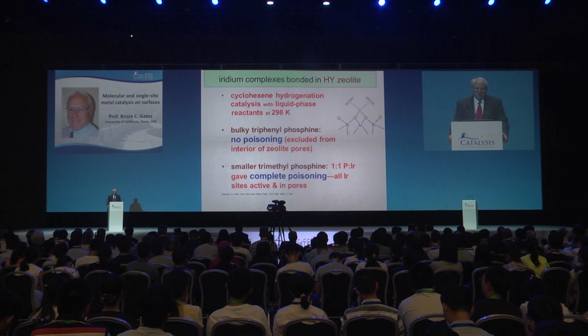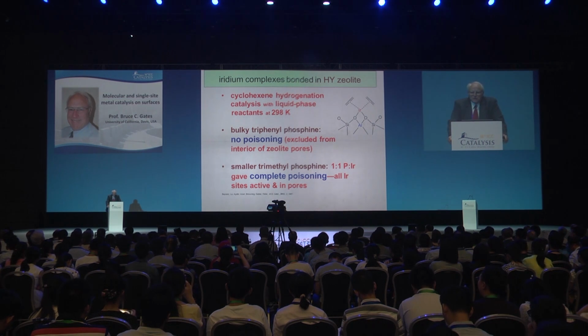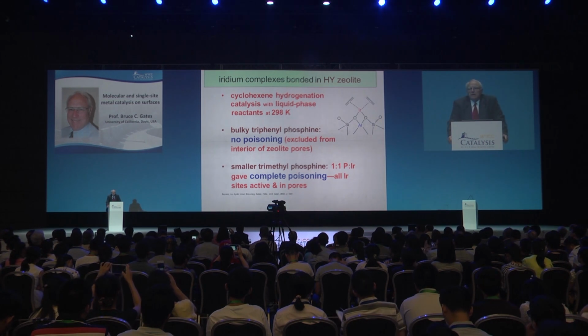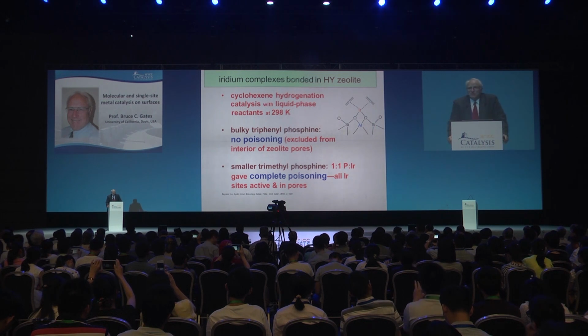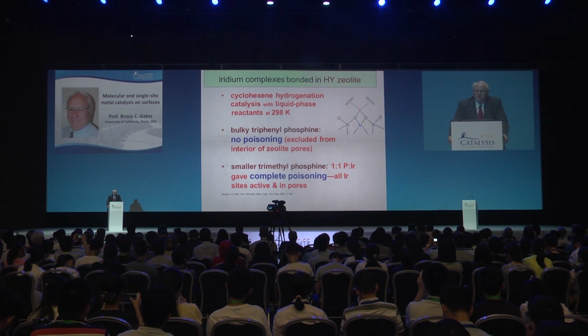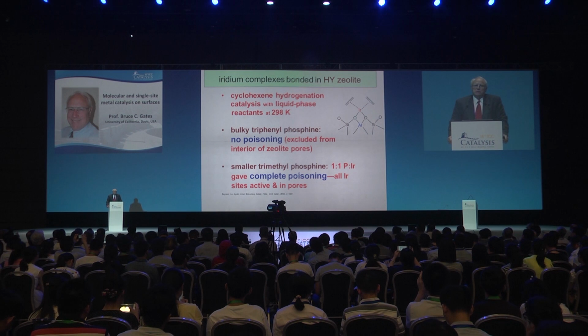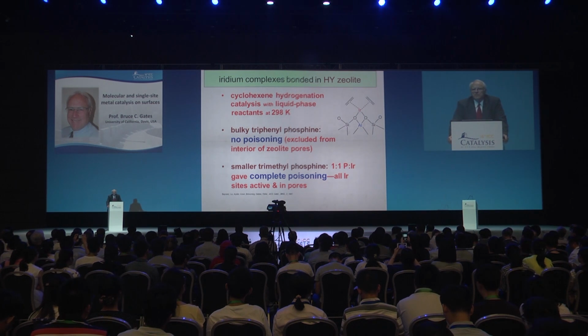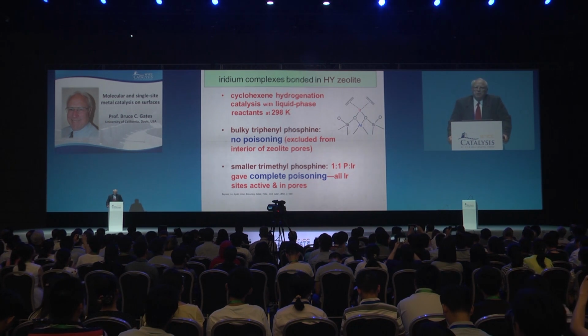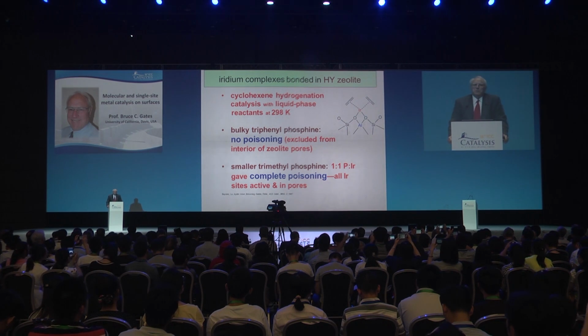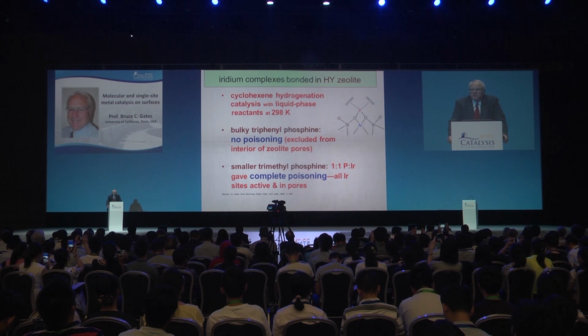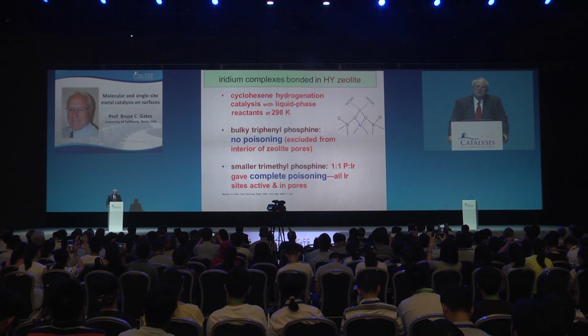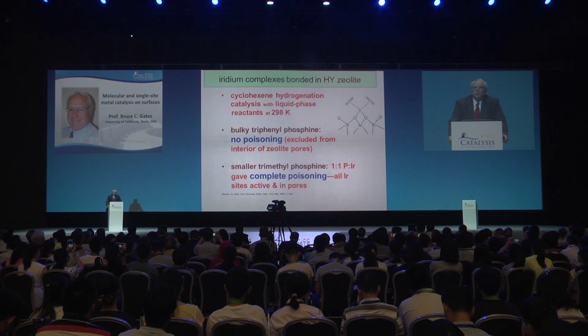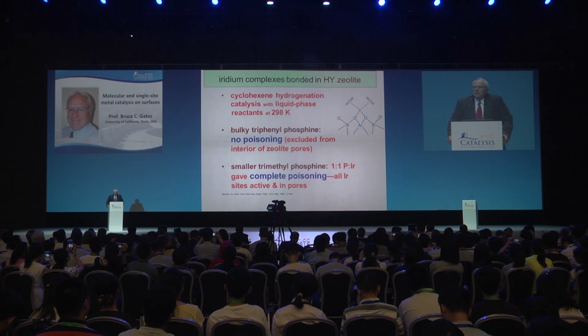Let's do poisoning. If we have this iridium complex bonded in HY zeolite and try to poison the cyclohexene hydrogenation with a big phosphine, triphenylphosphine, it doesn't work. There's no poisoning because the phosphine's too big to get into the zeolite pores. Use a small phosphine, trimethylphosphine, and it poisons the catalyst. One person, one vote. One phosphine, one iridium site.